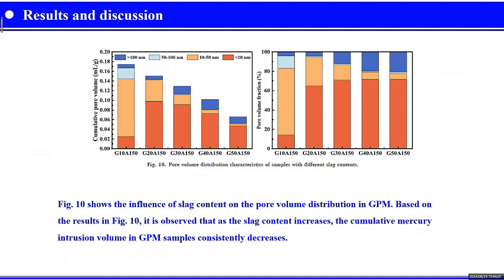This is mainly because excessive slag content can lead to too rapid polymerization processes, making it difficult for some precursor materials to participate in the polymerization reaction in time, thereby generating certain large capillary pores.